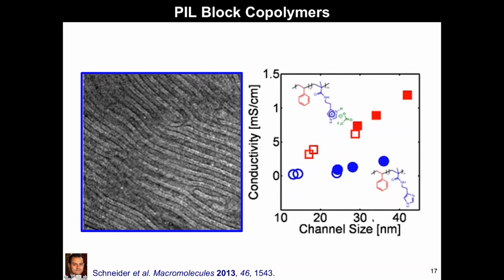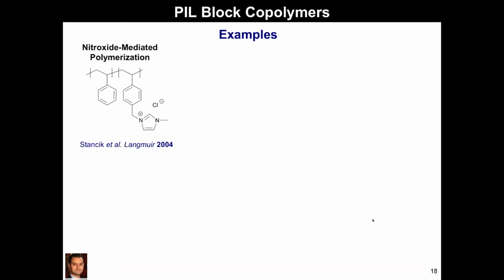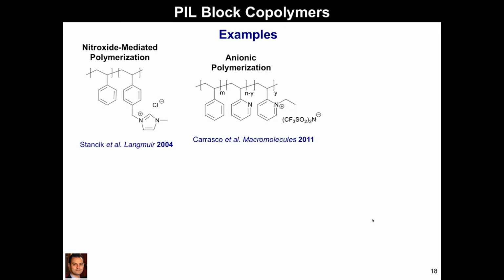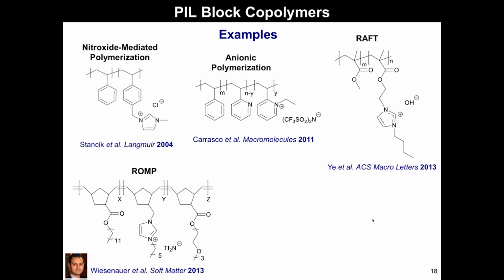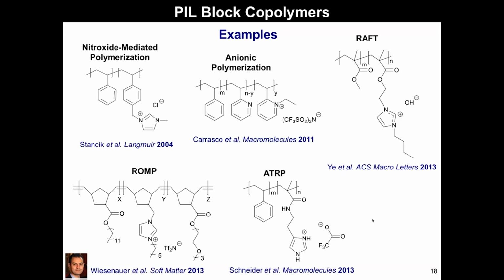So you definitely see these are just several examples of how morphology can impact ion conductivity in single ion conducting PIL block copolymers. The other interesting feature here is that recently a number of people have shown that you can make these from a variety of different polymerization techniques. Here is an example of nitroxide mediated polymerization, anionic polymerization, RAFT, ROMP, and also ATRP.